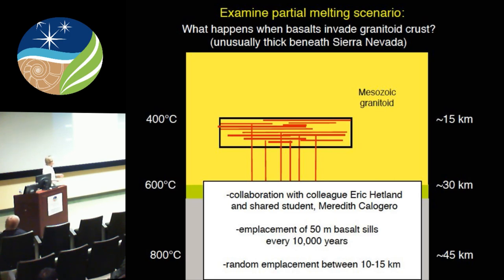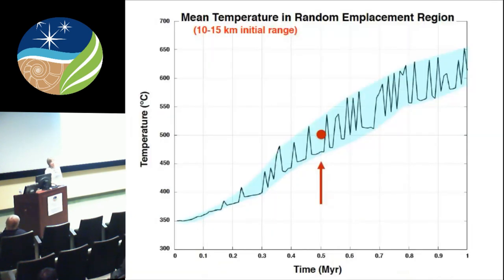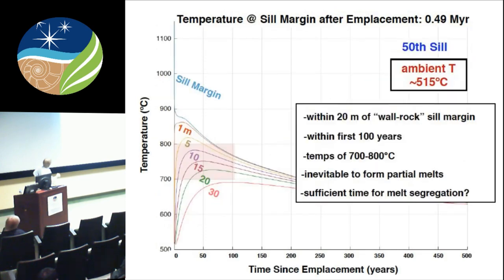If we just choose an emplacement rate of 50 meters every 10,000 years, and we can look at different rates, randomly emplaced, what we see is that the ambient temperature starts to heat up in this mixed lithology volume of the crust. And if we look at after 500,000 years, when the ambient temperature of the crust is only a little over 500 degrees C, what we see is that when you first put in a sill, the margin of the sill, and this is 1 meter from the sill, 5, 10, 15, sees temperatures between 700 and 800 degrees in the first 100 years. And so if the ambient temperature is 550, 600, it's going to be even more.